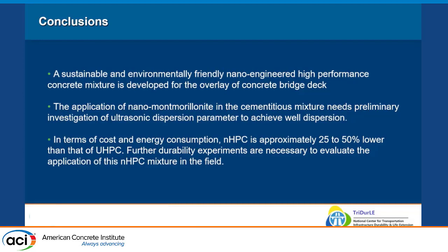So now I would like to conclude my presentation. We developed a sustainable and environmentally friendly nano-engineered high-performance concrete mixture for application as an overlay on concrete bridge decks. For the application of nanomaterials, especially nanoclay, in cementitious mixtures, it needs a preliminary investigation to obtain the optimal ultrasonic dispersion parameters, like the dispersion time, so that the nanomaterials can be well dispersed in the system. And finally, in terms of cost and energy consumption, nHPC is approximately 25 to 50% lower than that of UHPC. But further durability experiments are necessary to evaluate the application of this product in the field.